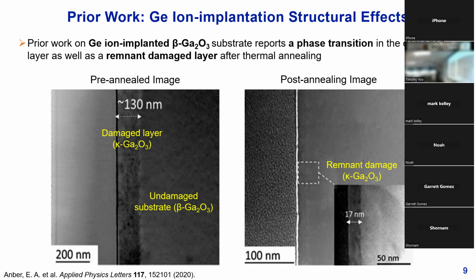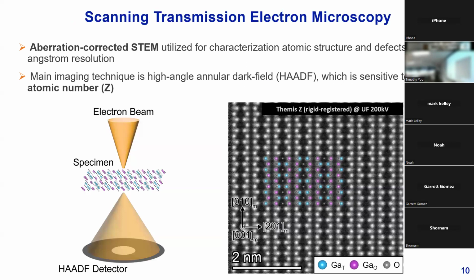While these prior works have really set a good precedent for us in terms of what needs to be done and what's been accomplished with this material system, there's still a lot left to be desired, specifically needing an atomic scale foundational understanding to confirm this type of defect structure, as well as that underlying phase transition. Of course, how we're going to do this is with scanning transmission electron microscopy. Aberration corrected STEM in particular gives us sub-angstrom resolution imaging, which is really ideal for characterizing atomic structure.